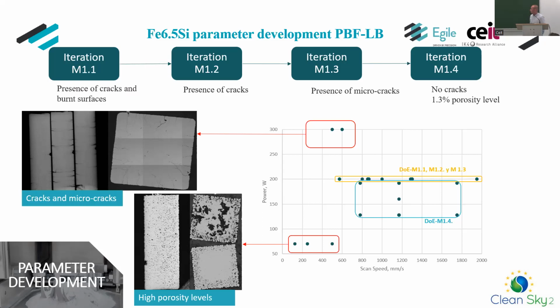In order to understand how this technology works, as you can see, when using high energy density levels, you get not very porous sections, but cracks and micro cracks have appeared on the CT scan and the metallographic test. When using very low energy density levels, we get no cracks, no micro cracks, but very porous structures not suitable for this application. As you can see, our design of experiments has checked different powers and different scanner speeds on the diagram.